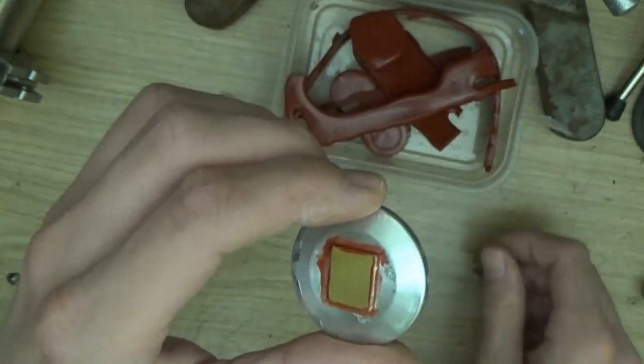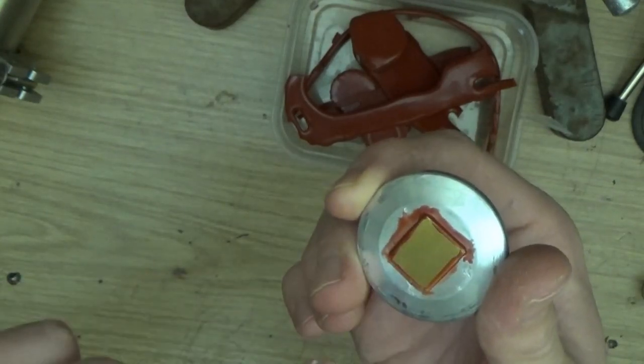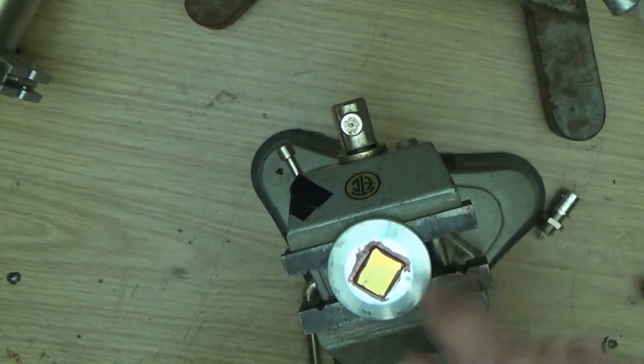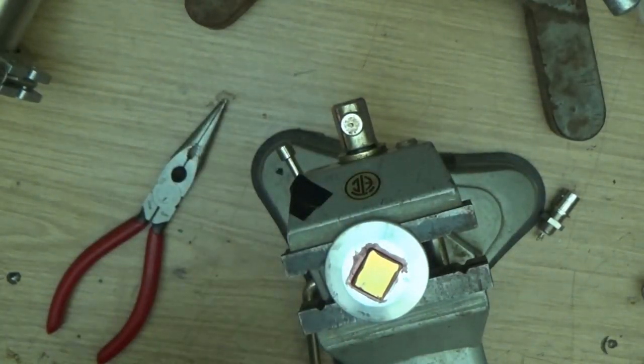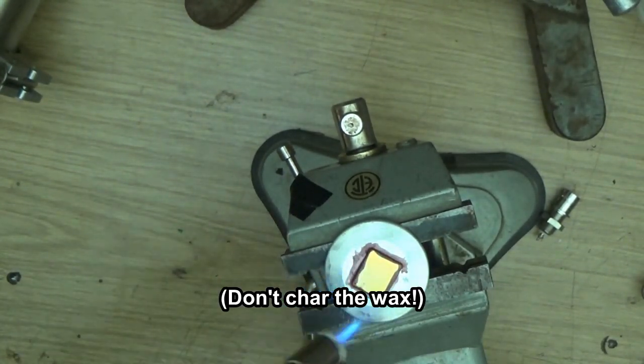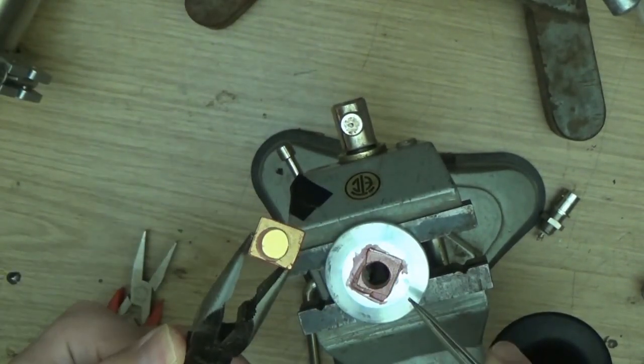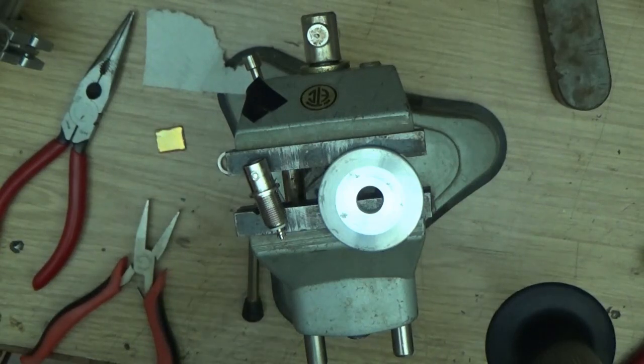So let me first show you how easy it is to detach. Again, that's the other good thing with these waxes. Getting rid of this seal again is tremendously easy. I'm going to grab some needle nose pliers. I'm going to put the part here and I'm just going to torch it for a tiny bit. And then I should just be able to lift the little plate off. Like that. This wax comes off very easily with a little bit of acetone and a rag. Which is perfect because when you seal stuff like this, you really should degrease it anyway.